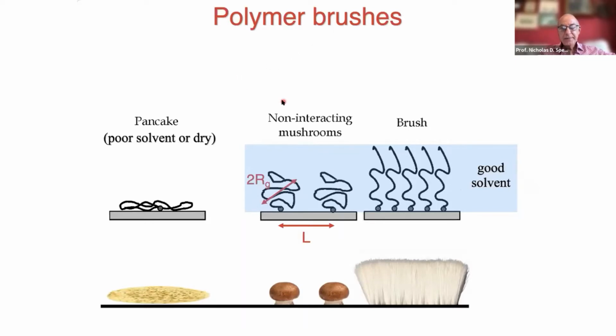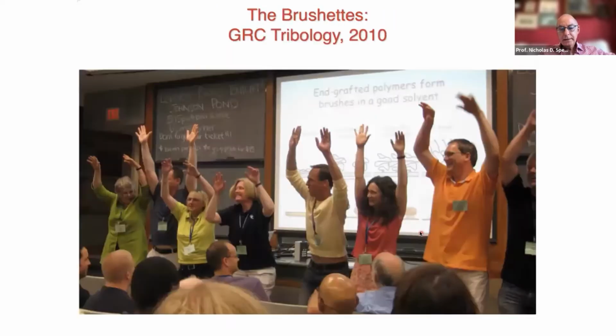Okay, got it. And then if they're closely grafted, then the interaction with the solvent is more energetically favorable than the interaction between the polymer chains. So they try to keep away from each other and spend more time with the solvent. And this means they have to stretch out against their entropy elasticity, and they form this brush-like configuration. Here are some tribologists imitating polymer brushes. You may recognize at least one of them.